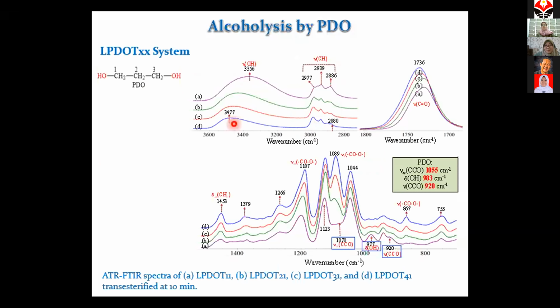In every system, we vary the ratio between PLA and alcohol, we vary the time, we vary the type of alcohol, and then we look at the structure of the final products. For example, if we look at this peak right here, the intensity of this peak can tell us the length of the final products.